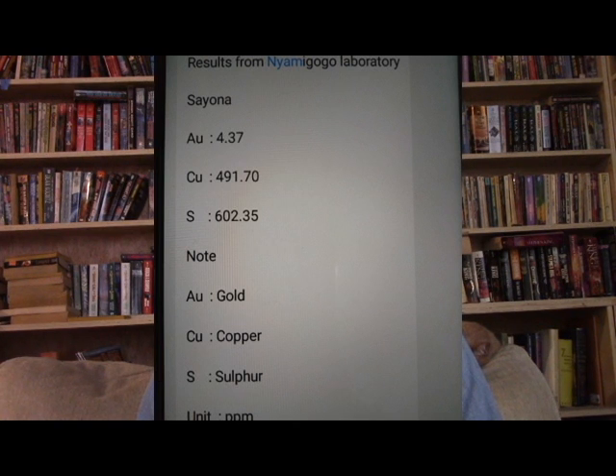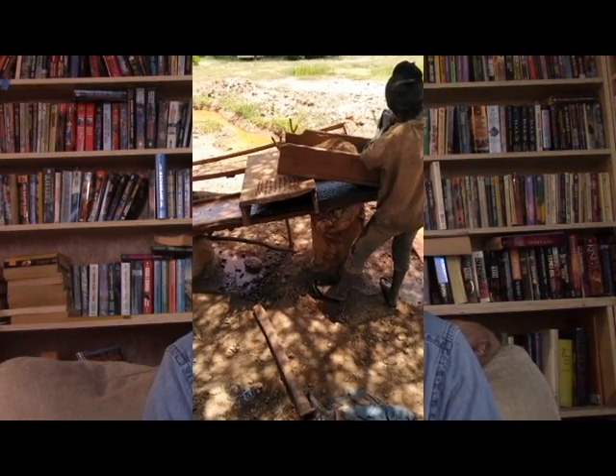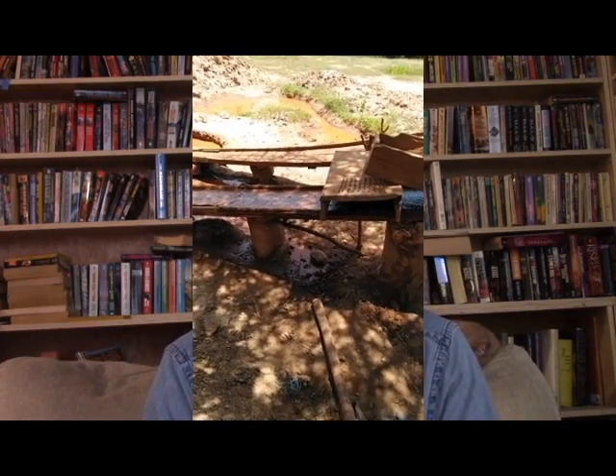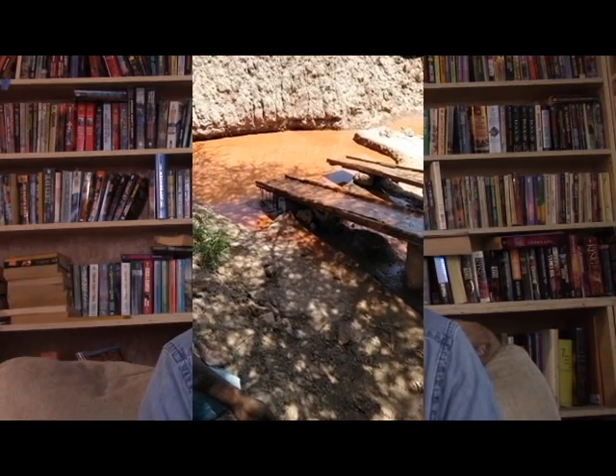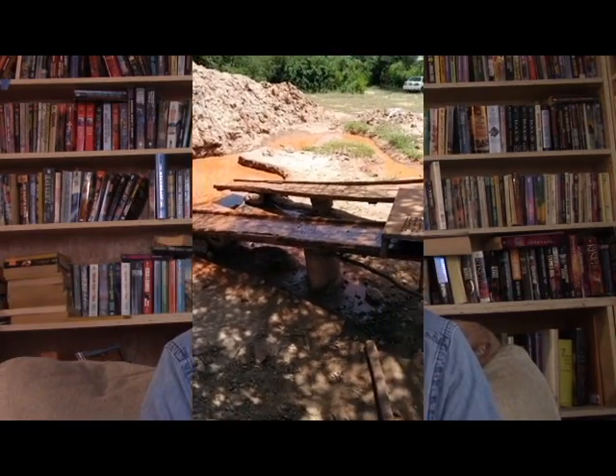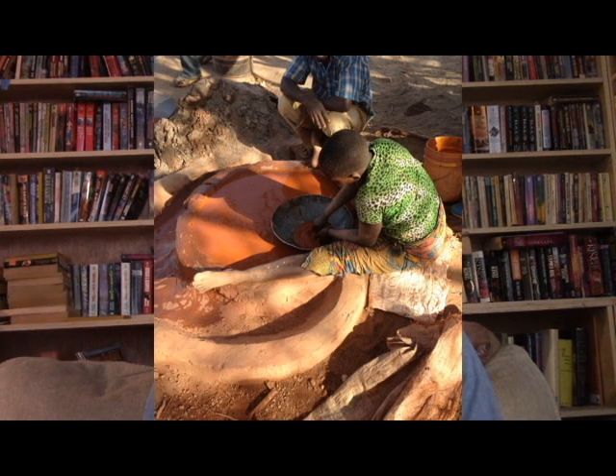I have one assay sheet that's done from an actual laboratory. They often will take 80 to 90 kilogram samples over to the locals who will sluice it over like a corduroy table sort of thing, and then pan it down and actually recover gold. They report roughly about 0.4 of a gram for an 85 kilogram sample. Works out, if I'm not mistaken, about 4.7 parts per million, about 0.15 ounces per ton, or about $200 a ton.